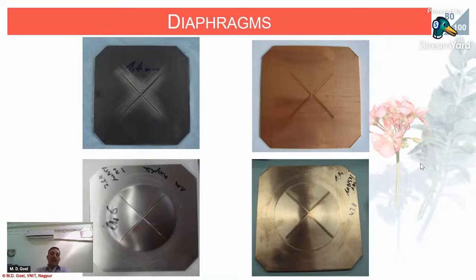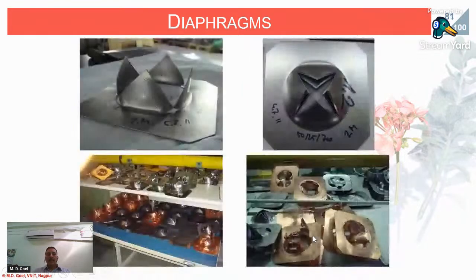So we fired this, and this does not open fully. Here in the down line, left side down image, you can see it was deformed, but it was not opened fully. So that's why the shock could not travel to the other end. Same thing happened with this one. We tried several combinations, and finally we were able to. Sometimes it was partially opened here, where you can see my cursor, and at the end finally we were able to achieve how it shall open.